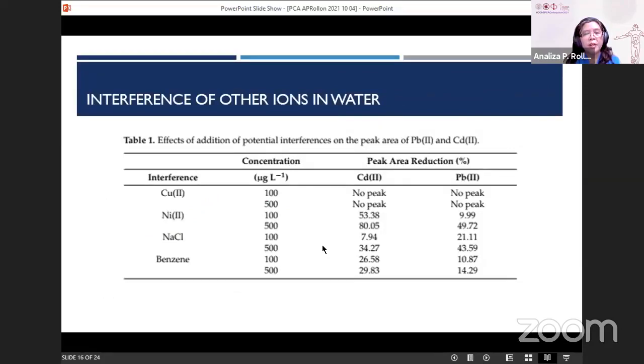And for the effects of interfering ions, we have here copper 2 at 100 and 500 micrograms per liter concentrations of copper 2. There is no peak that can be seen, both for the detection of cadmium and lead. Whereas for nickel, at 100 and 500, for cadmium, there's about a 54% reduction in the peak area and 80% at 500 micrograms per liter concentration of nickel.